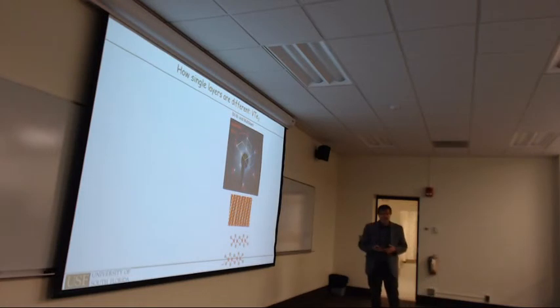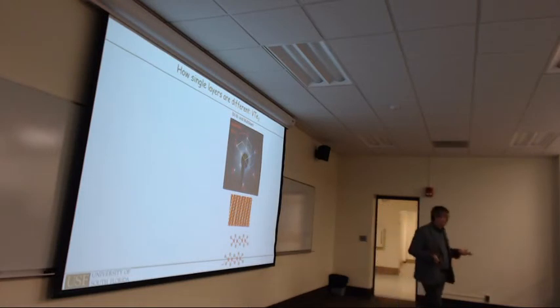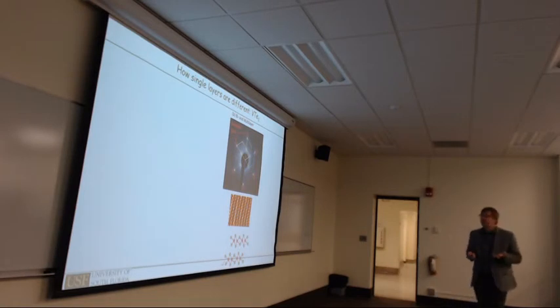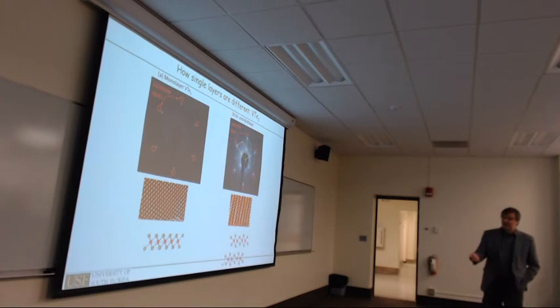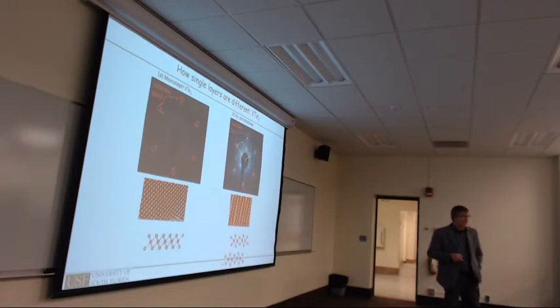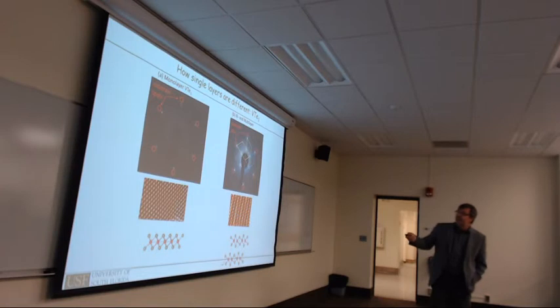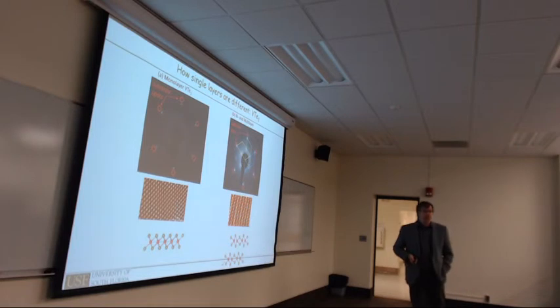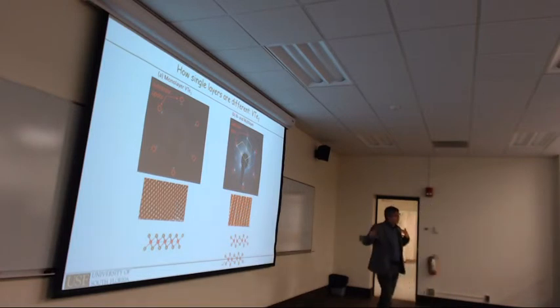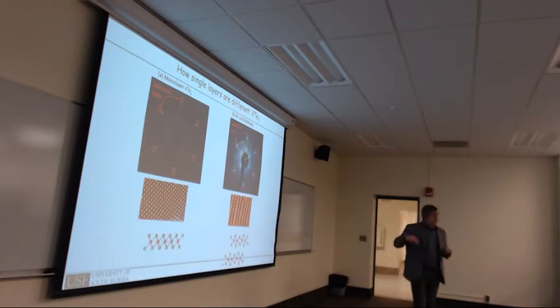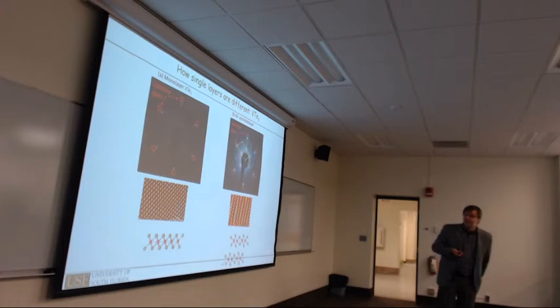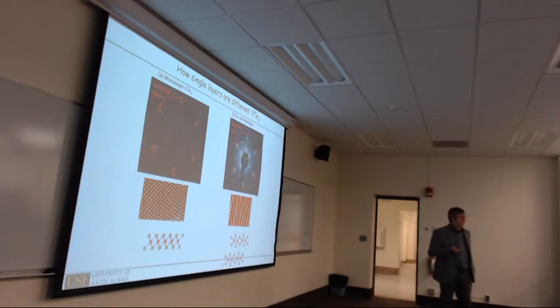And the simplest way to answer that is to grow the monolayer and look at the structure of the monolayer, where you don't have any interlayer interaction by definition. So if you do that, then behold, you really get just a simple structure. You get a nice hexagonal pattern, and you see that also in low energy electron diffraction, where you again have the substrate spots here of the molybdenum disulfide, and then you have the really sharp vanadium ditelluride spots. So you get a structural transition in vanadium ditelluride as you reduce the thickness to a single molecular layer, and we believe that is due to interlayer interaction between the tellurium atoms.